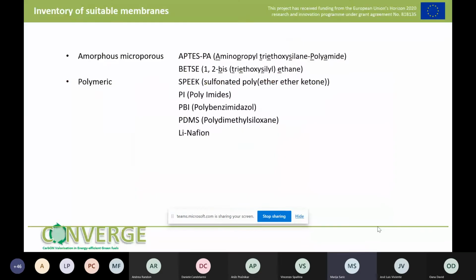We made an inventory of the membranes that we will test for this application. We selected 7 membranes, of which 2 were the amorphous microporous hybrid silica membrane. At TNO, we have a lot of experience with these membranes for pervaporation, but we also tested them in gas separation processes. And we selected 5 types of polymeric membranes.